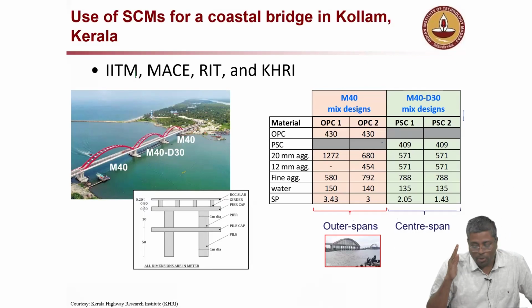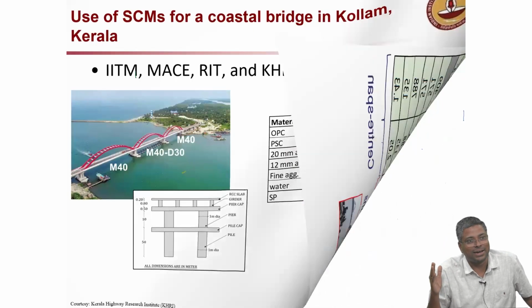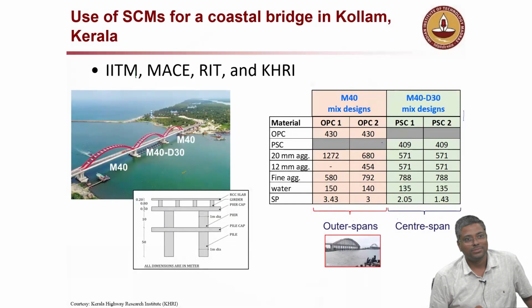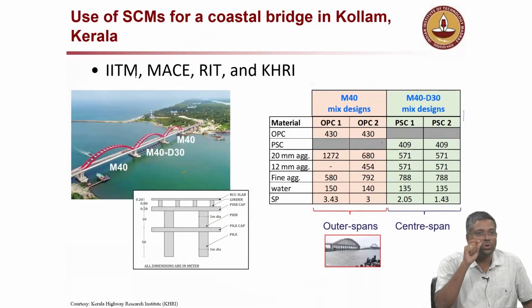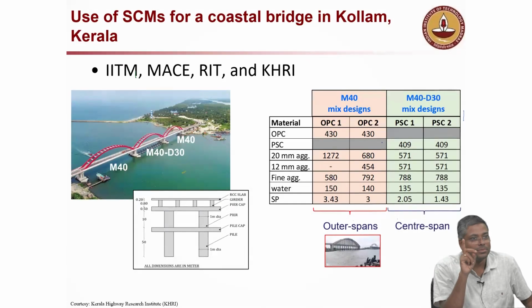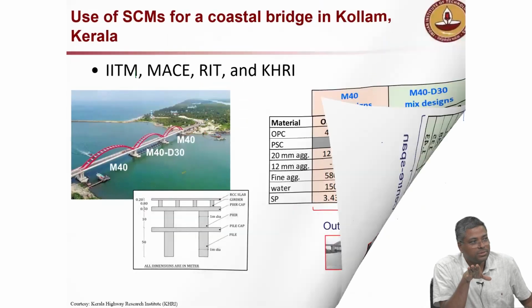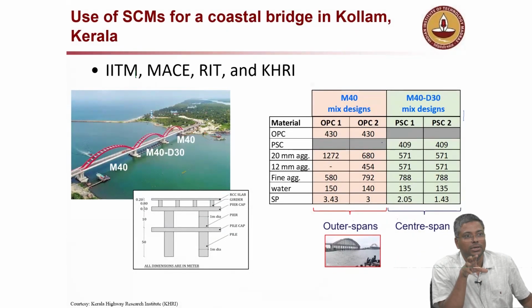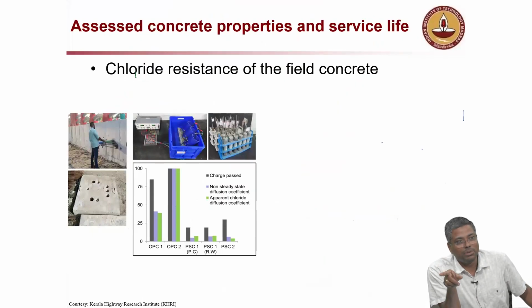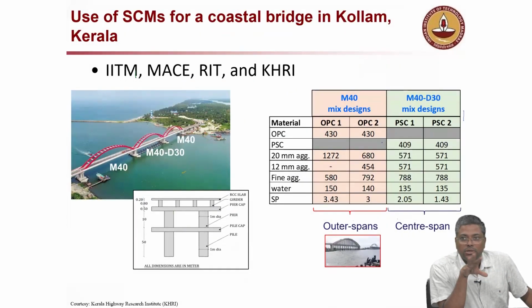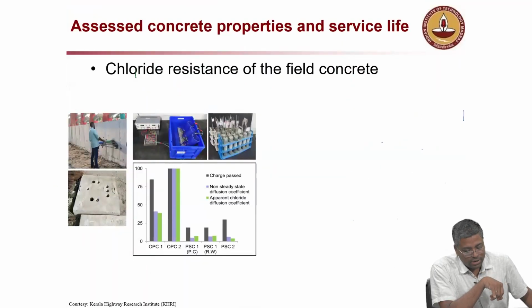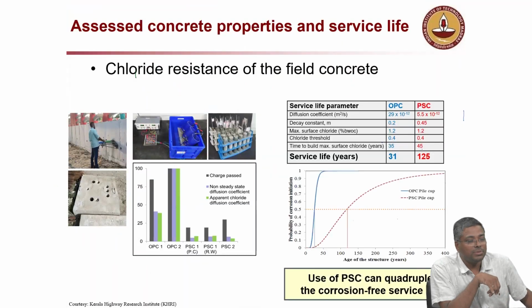The point I'm trying to make is that you don't need 600 kg cement, you don't need 500 kg cement, 400 is enough. The trick is to have the aggregate gradation proper and use adequate chemical admixtures. That's where the trick is. And you have to do it at the site with your kind of aggregates, your kind of cement, your kind of admixtures. Compatibility between cement and admixtures, all that has to be looked at. Okay. Is it clear?